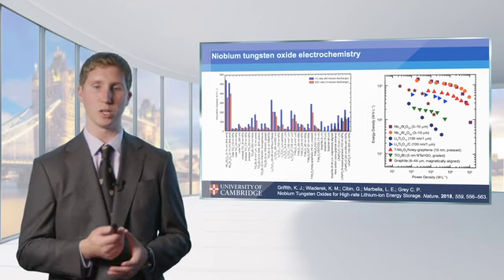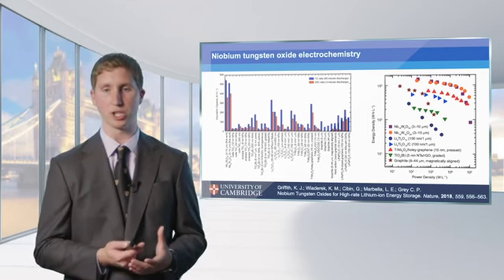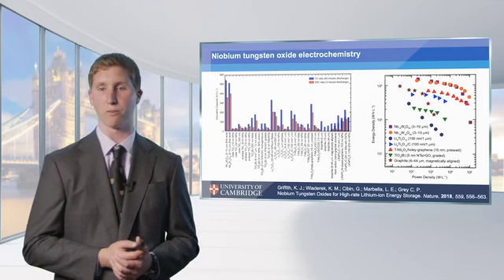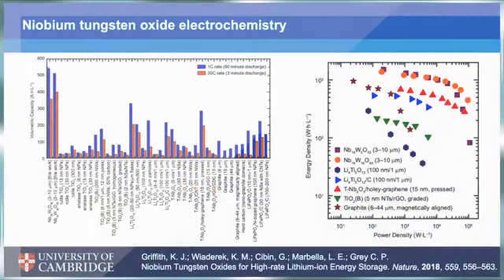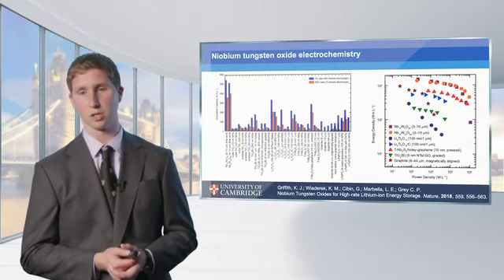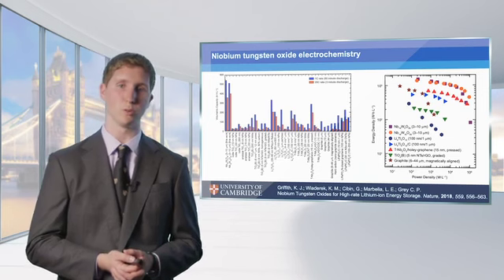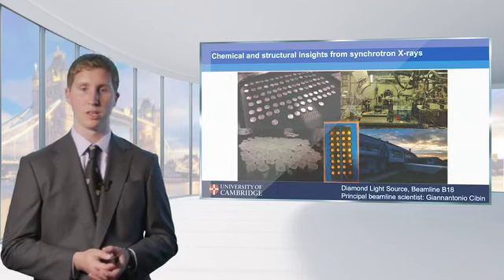And so if we look at this in a Ragone plot where we're comparing energy density and power density, what we find is that because of the high density of these particles, high volumetric densities, we're able to, over a wide variety of rates and powers, supersede even the best materials out there in terms of other nanostructured metal oxides, and also, of course, conventional lower rate materials like graphite, which fall off very rapidly as you approach high power densities.